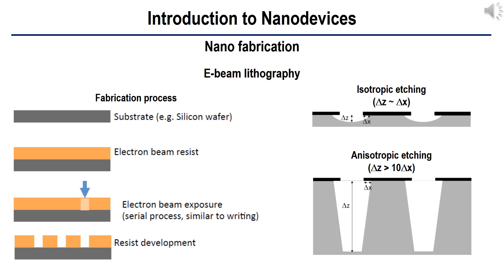Before exploring other patterning processes, it is instructive to learn about etching. Etching is a critical step in nanofabrication. While the resolution is determined by the light source and mask, the detailed shape and contact properties of different materials in the chip are determined by the etching. By controlling etching methods, etching isotropy can be controlled. Gaseous etchants typically produce isotropic etching, where depth and planar etching rates are nearly the same. In contrast, anisotropic etching can increase the depth-direction etching rate by 10 or more times compared to the planar direction — which is important for fabricating three-dimensional nano-features. For anisotropic etching, plasma etching such as ion bombardment can be used, where heavy ions collide with the substrate vertically.